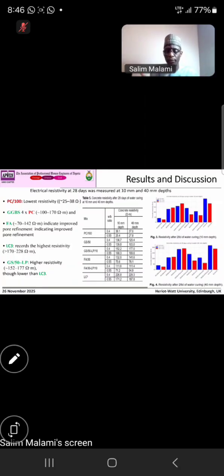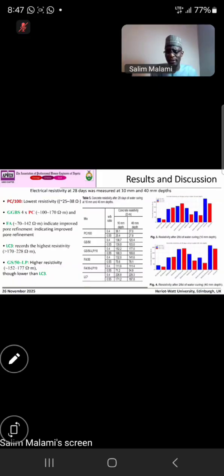for easy explanation. It was measured at different depths, as I said, we embedded different pins at different depths. So here I reported for 10 millimeter and 40 millimeter. The reason for using 10 millimeters is that it is close to the cover of the concrete, so you can easily assess it. For 40 millimeters, most concrete cover, like here in Europe and the UK, they use 40 millimeters, especially in chloride ingress environments. For a normal, non-aggressive environment, the nominal cover is 25 millimeters, especially in Nigeria.